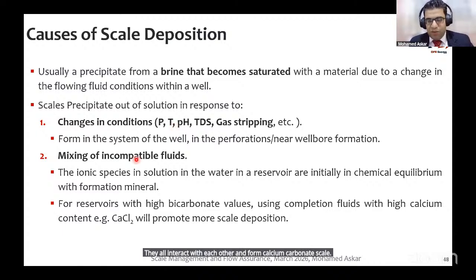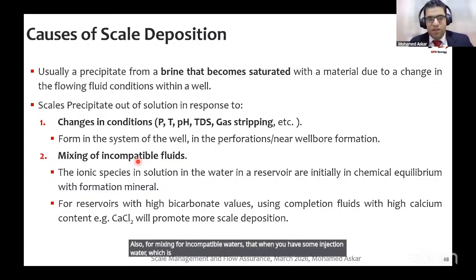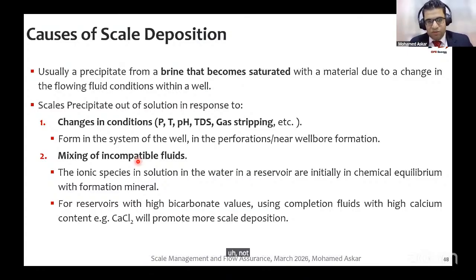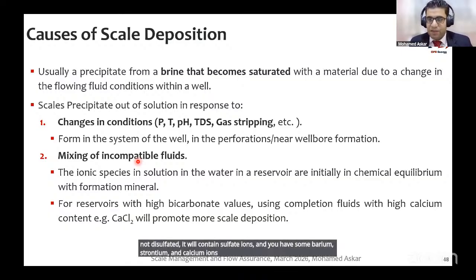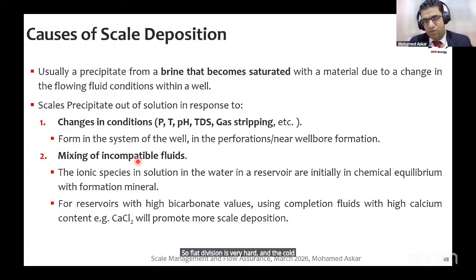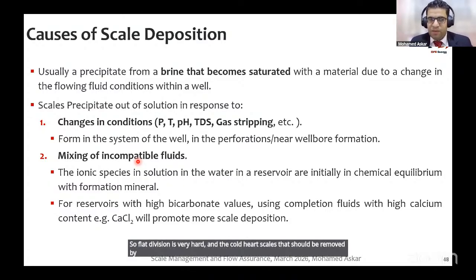Also for mixing of incompatible waters, when you have some injection water, which is mainly seawater, not desulfated, it will contain sulfate ions, and you have some barium, strontium, and calcium ions inside the formation water. When you mix the formation water and the injection water, they will promote some scale deposition, especially sulfate. Sulfate deposition is very hard, and they are called hard scales that should be removed by milling, maybe by coiled tubing or by special chemicals like DTPA or EDTA, as we stated.